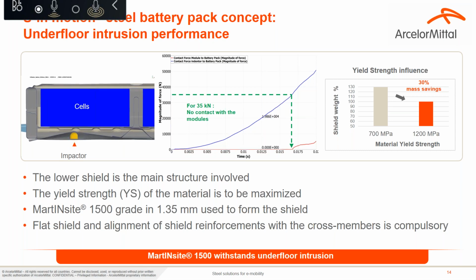In this case, you can see that reducing the yield strength from Martensite 1500 to 700 MPa, you lose 30% weight. So it's again more important to use Martensite 1500. In this case, we reached the target with a thickness of 1.35 millimeter.